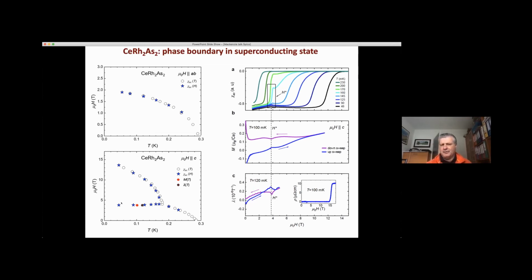There's definitely a thermodynamically established almost horizontal line here, which is a phase transition separating two different kinds of superconductor. Okay? And as I say, that's only been seen a couple of times previously in the whole history of superconductivity. So we were very gratified to see that. And that observation experimentally is the main experimental part of this talk. Whether or not the theory is right, of course, Dan's here, so the theory is right, that I'm going to show you in a second. We have an experimental result here.